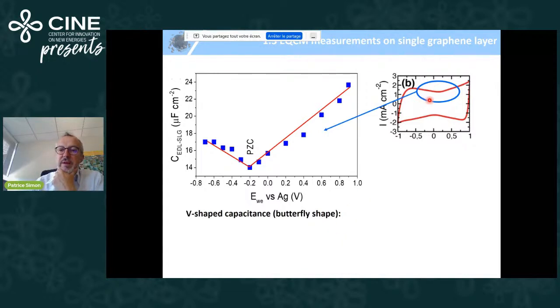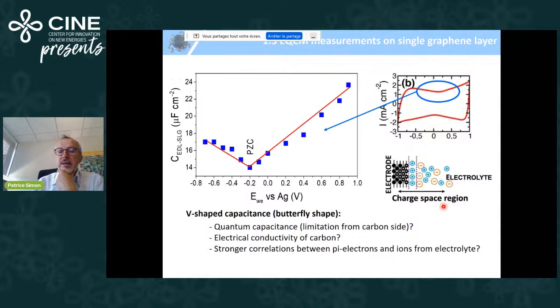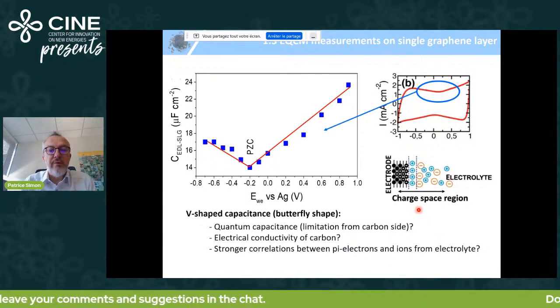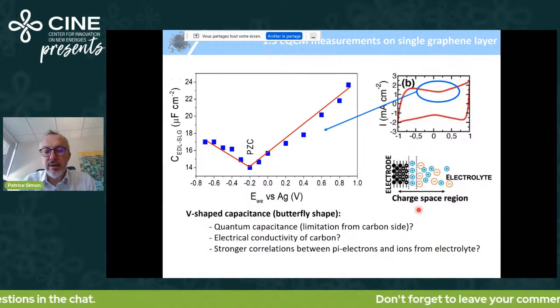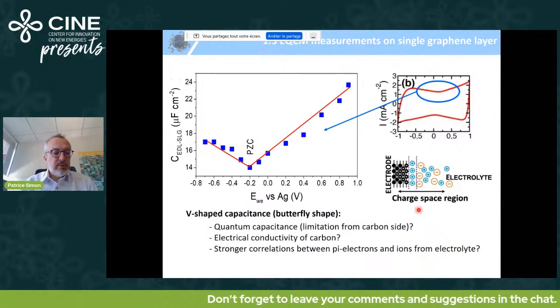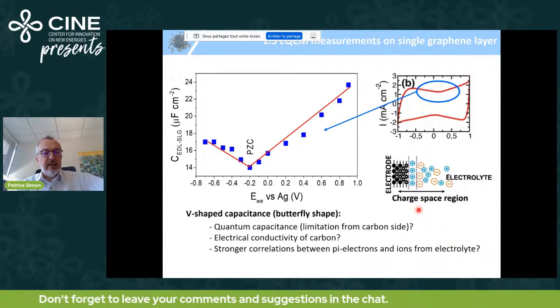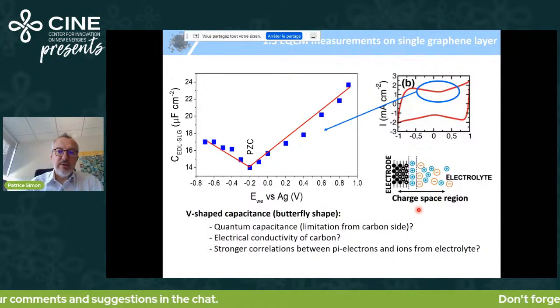First one, people claim that this butterfly shape observed with, for instance, carbon nanotubes corresponds to a minimum of conductivity of the carbon nanotubes. Other people, more recently in Nature Nanotechnology, this is Professor Zhu's work in Hefei University, explain this V-shape capacitance change with the existence of a space charge region driven by the quantum capacitance of the single layer graphene, which is in fact, from their view, linked with a limited charge carrier density on the single graphene layer. And other people mentioned that you have strong correlations between ions and the carbon surface. So in this case, this could also explain this specific behavior.